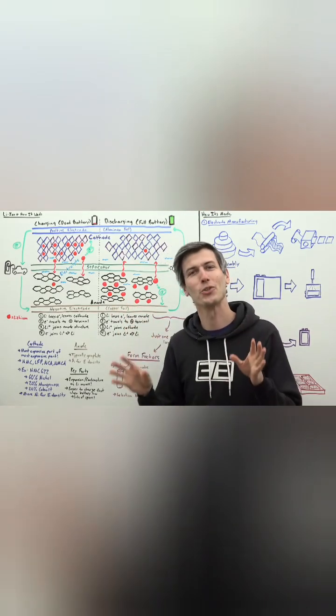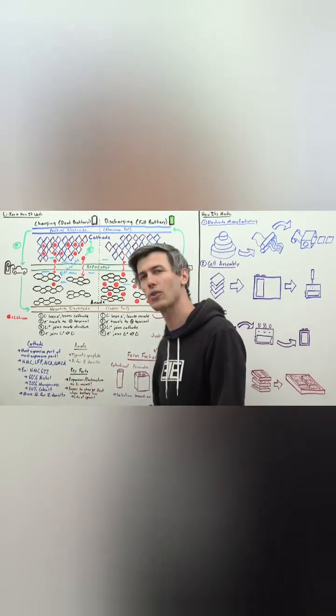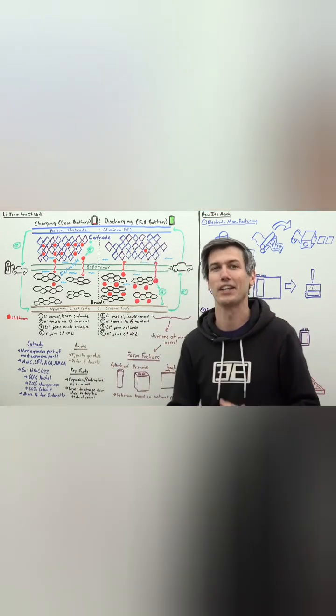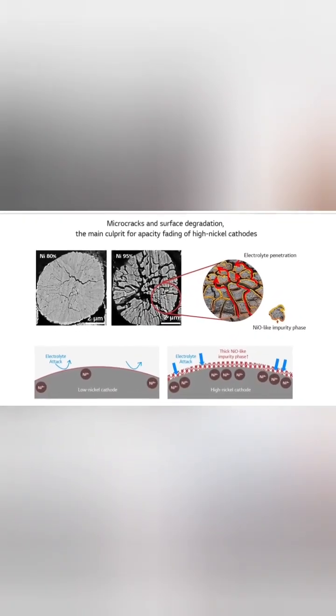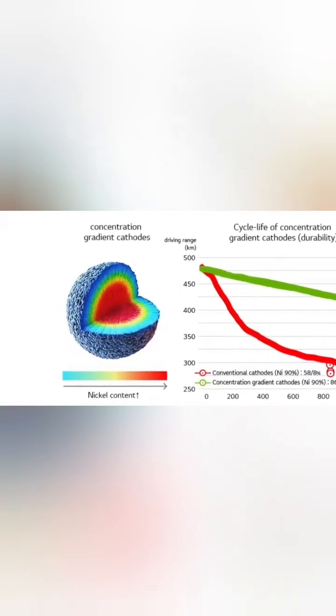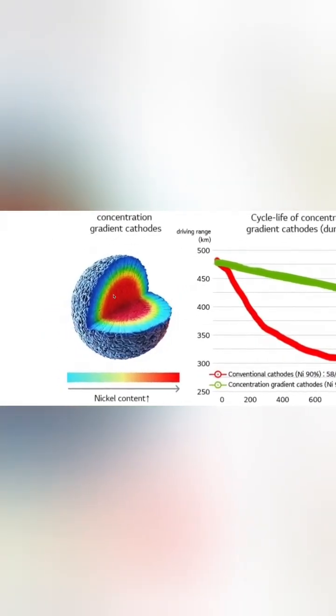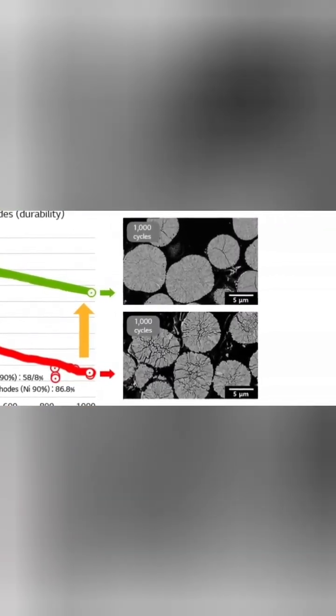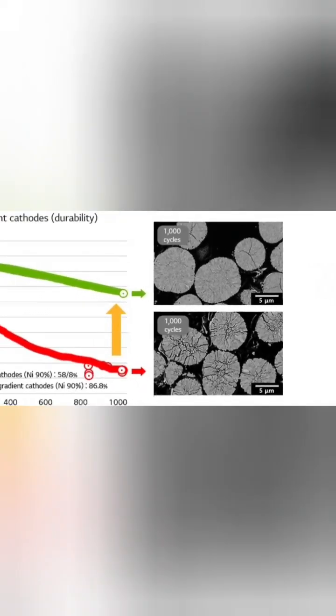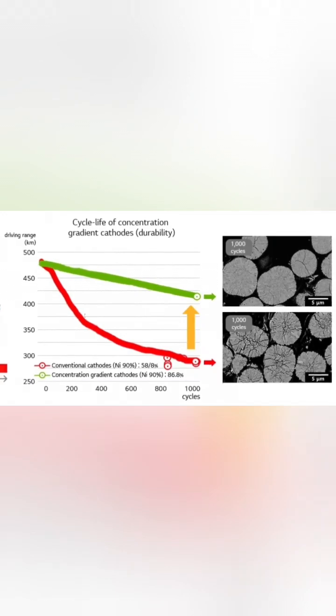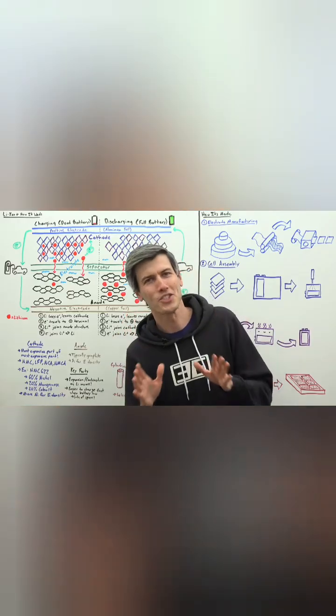Now, we're probably getting too deep too quickly, but increasing the nickel content of the cathode is actually a really interesting discussion. Using higher percentages of nickel tends to cause micro-cracking of the cathode, as well as increasing reactivity with the electrolyte. But you can actually use higher concentrations of nickel by using a gradient in the cathode, with higher nickel concentration in the center and less at the exterior. This results in a particle that's less susceptible to microcracking and has less surface reactivity with the surrounding electrolyte. So you get improved energy density without the major drawbacks of using high nickel content. Okay, that's just one component.